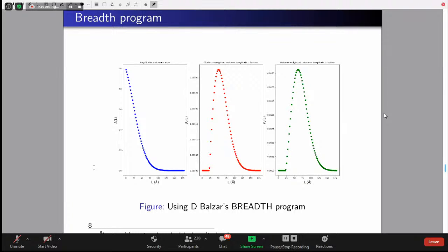In a sample, let us suppose I have 30 nanometers of crystallite size. It means that is an average size of 30 nanometers, but inside it will have a large distribution. There will be crystallite sizes which are much larger than 30. There are crystallite sizes which are much smaller than 30 nanometers. So this is the distribution.